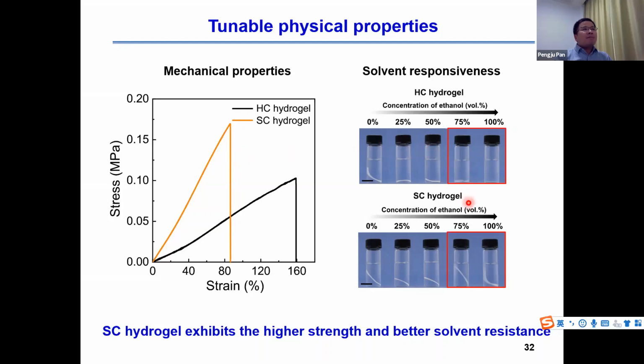Stereocomplex hydrogel also has better solvent resistance than the homo-gel. The homocrystalline gel breaks in a water-ethanol mixed solvent at high ethanol concentration. However, the stereocomplex hydrogel can sustain the same condition.